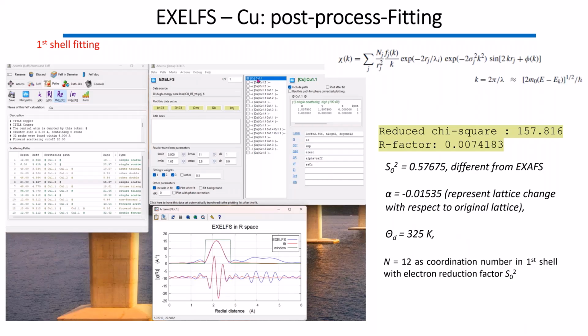So by fitting the first shell, you can list your fitting and choose different parameters so that you can do the fitting properly. Of course, you also need to choose this parameter according to your dispersion and so on, so basically the optical setup. And you can see the fitting results show a very consistent number, we'll talk about this later. But this amplitude reduction factor is something like 0.6, which is a bit different from X-ray, which is roughly 0.8 to 0.9. And that's literally what I mentioned before, there will be a difference between electron interaction and X-ray interaction.